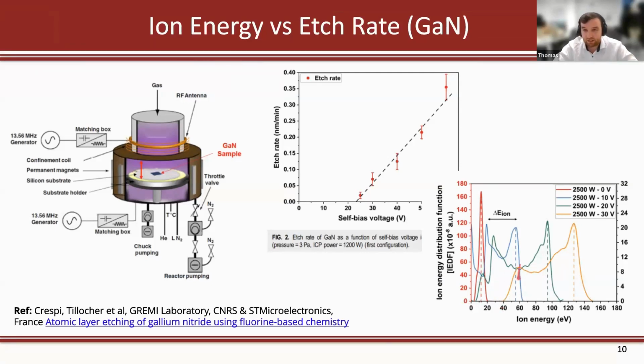So if you want to calculate what the etch rate is, you have this data here, but you have to multiply this by this and this by this, and you can see here that this is showing small shifts in bias. So let's say you're delivering constant power, but the matchbox is heating up and less power is being delivered and your bias voltage is dropping. That means mid-process, your etch rate is dropping, right? Your etch rate is changing because the ion energy is. So the control and measurement of this is kind of critical.